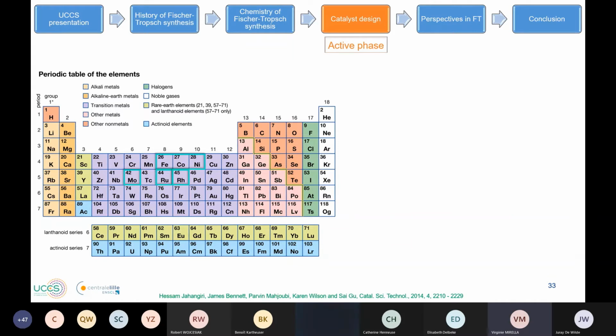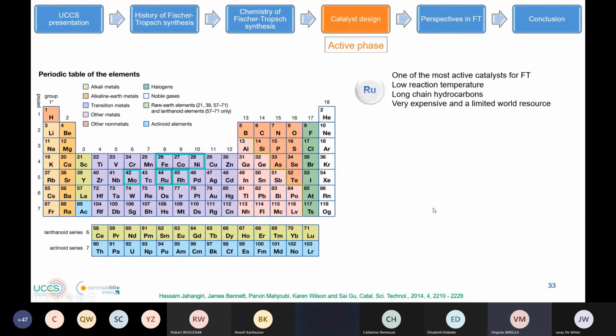So in terms of active phase, usually in the beginning, the first active phase was cobalt, discovered by Franz Fischer and Tropsch. It was cobalt, but then afterwards they also studied iron. So iron and cobalt are historically the first active phases for Fischer-Tropsch synthesis. But there's also a lot of research made on ruthenium. Ruthenium is one of the most active catalysts for Fischer-Tropsch synthesis. It works at low temperature. But ruthenium is mainly for producing long chain hydrocarbons, and it's very expensive and limited in the world. So we are not going to use ruthenium to produce olefin.